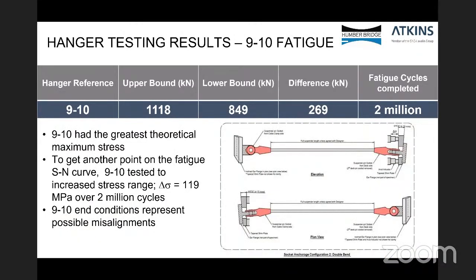this shows the test setup. In this instance, we assumed that one of the bottom hanger sockets had seized in rotation, which would cause additional bending stresses to the hangers. So for that reason, we tested the 2 million cycles with two bends, one at the bottom and one at the top. Rather than testing at a similar stress range as the previous hanger, we've tested at an increased stress range, as I've said, of 119 newtons per millimeter squared. Can you go to the next slide, please?